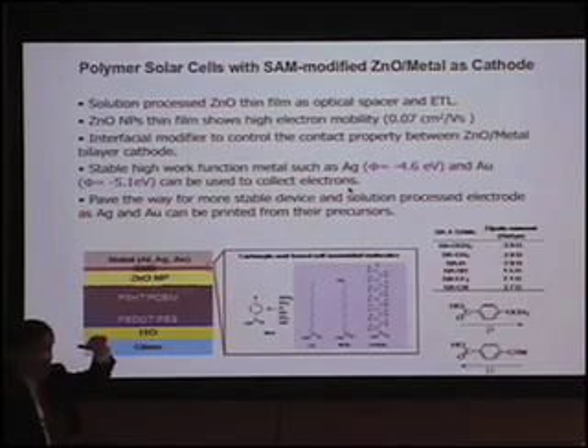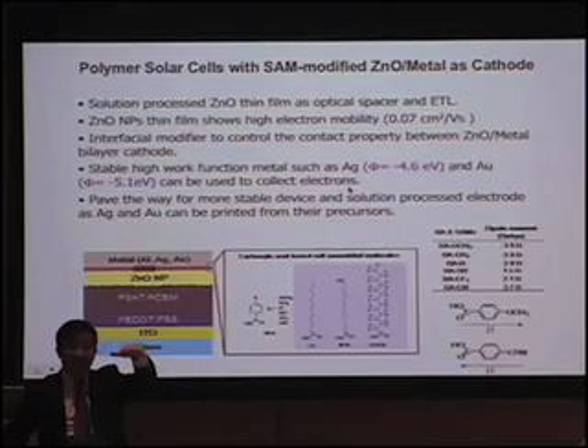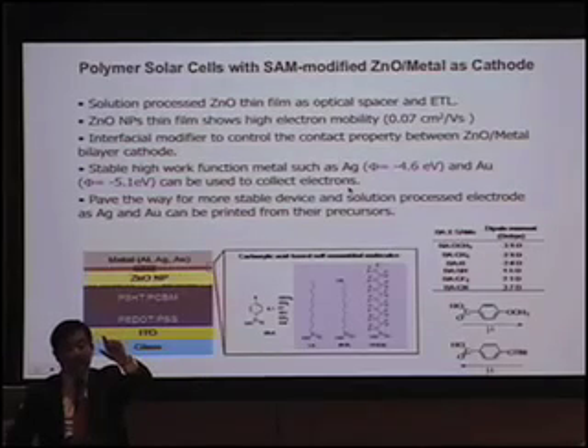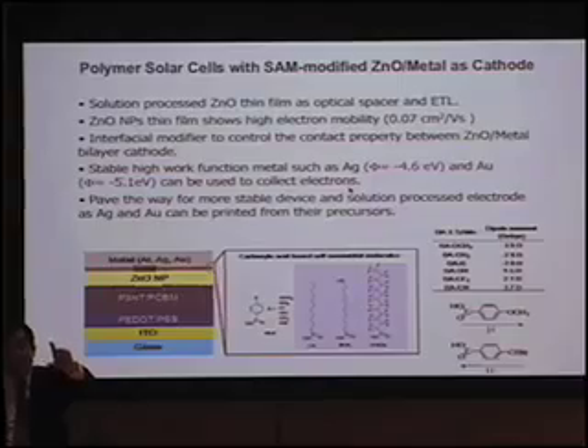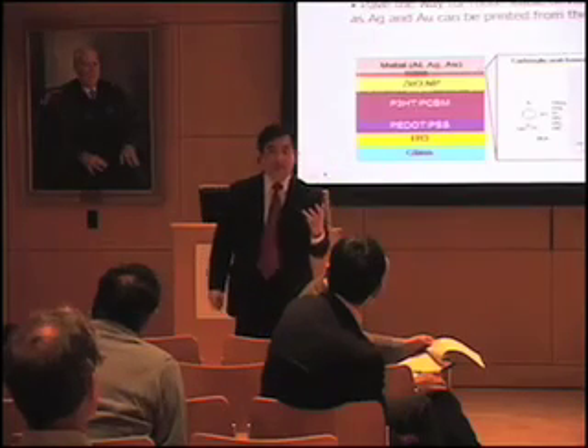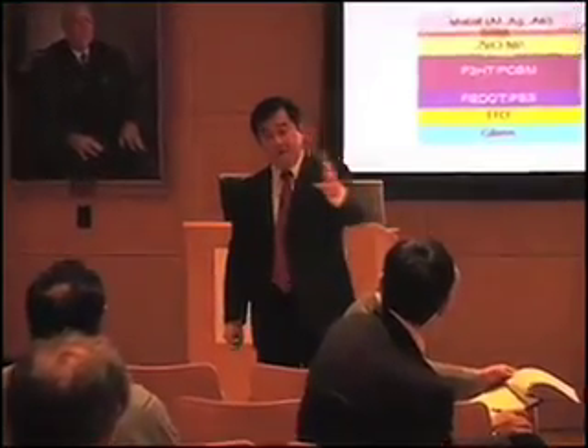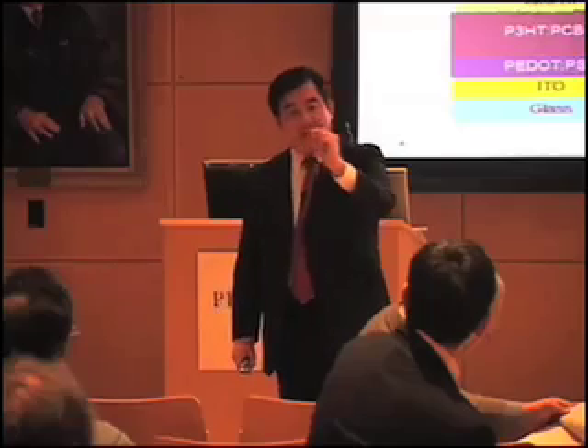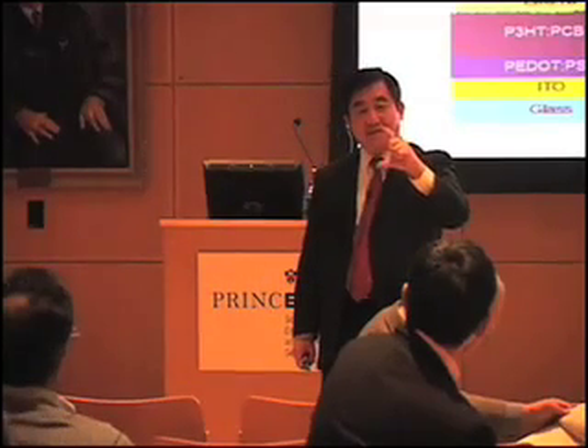So instead of using a low work function metal as a cathode to collect electrons, I can use a high work function metal, which originally has a relatively large energy barrier and cannot really give you the maximized open circuit voltage. You only have a very small VOC. Now, depending on the dipole I use, I can get the maximized VOC out of that. So in that set of experiments, I'm trying to show you that you can utilize SAM to optimize your open circuit voltage, but also you can get other benefits: a very nice low series resistance and also very high shunt resistance, which means you have less current leakage through those layers.